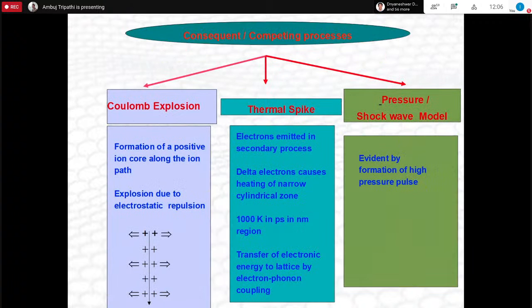And these are the three models, of which the thermal spike is mostly what we use. All this has been explained very nicely in the talk, so I will skip this part. But this is where you see how the electron temperature rises, and how the heat is taken away. Mostly you have heard in the talks the role of delta electrons, and how the temperature rises on picosecond time scales, and then energy is transferred to the lattice by electron-phonon coupling, through the coupled diffusion equations that were covered. So all that happens, and then you reach your material.